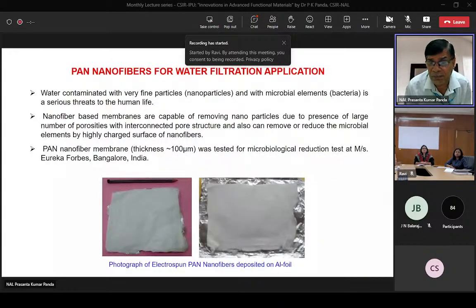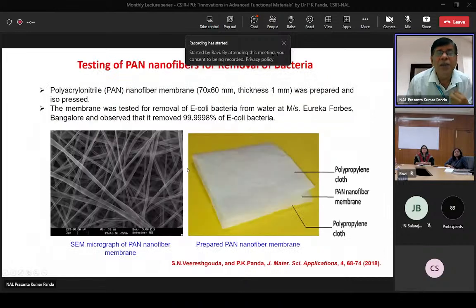And when the pandemic came, we thought of using this electrospinning technique to prepare PAN nanofibers, mainly for filtration of materials. In fact, we had tried earlier with water technology, where a DST project was sanctioned to make these PAN nanofibers. These PAN nanofibers of 100 micron thickness were tested for a microbiological reduction test at Eureka Forbes R&D Center, Bangalore. And what you could see in this case is that it completely removes E. coli bacteria, at the tune of 99.9998% of E. coli bacteria.